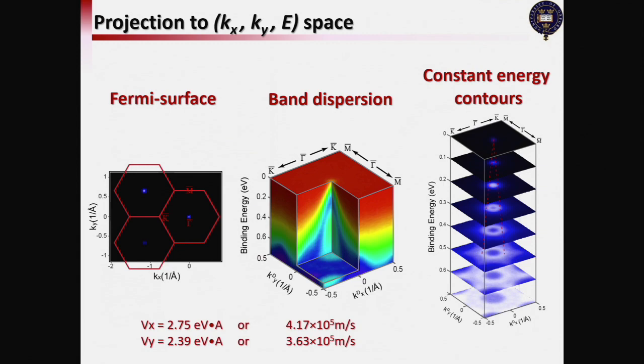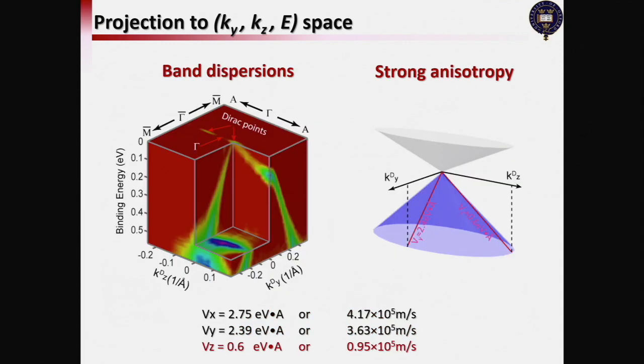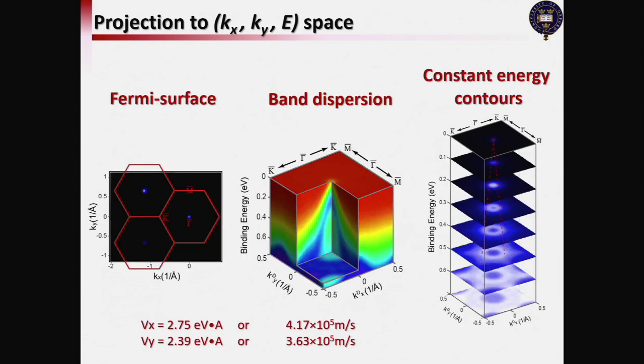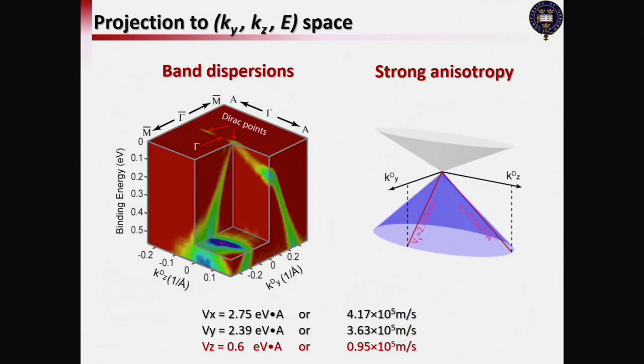And we projected the band structure to the kx, ky, energy subspace, and then we measured that and saw, well, it's a Dirac point, it's conical dispersion, and that's good. And then we projected it again to the ky, kz, energy subspace, which is orthogonal to the previous one. And we again saw a linear dispersion, but it doesn't exactly look like the conical shape here. It turns out it's a squeezed cone. Then you can see it's like this. And the squeezed cone means that the Fermi velocity along the two ridges is different. And the direction where the Fermi velocity is smaller is actually the z direction.